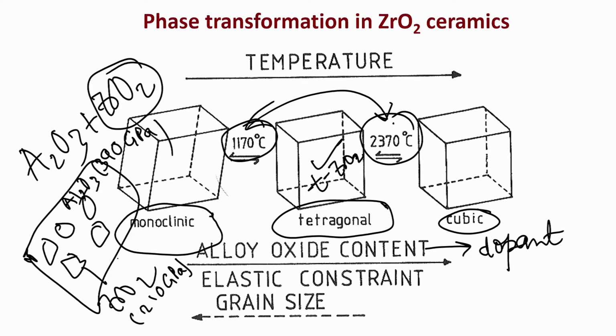Now, by dispersing zirconia in the alumina matrix, essentially you are allowing the zirconia particles to experience larger elastic constraint in their neighborhood, because all the alumina grains which are part of the alumina matrix have higher elastic modulus, and because of the elastic constraint, the high temperature tetragonal phase of zirconia can be retained. Essentially, it will not allow tetragonal to undergo phase transformation to the monoclinic phase. So, I repeat, there are three effects which influence the zirconia phase stability. The first one is the dopant content, second one is the elastic constraint, and third one is the grain size.